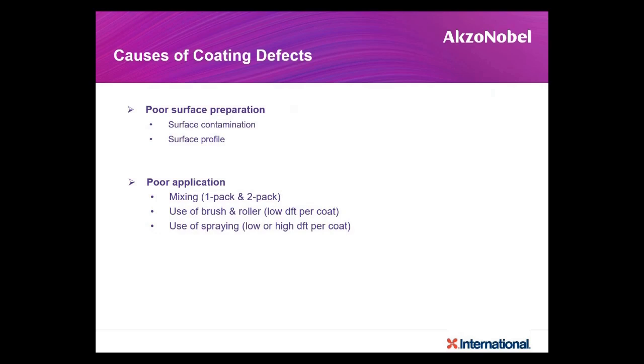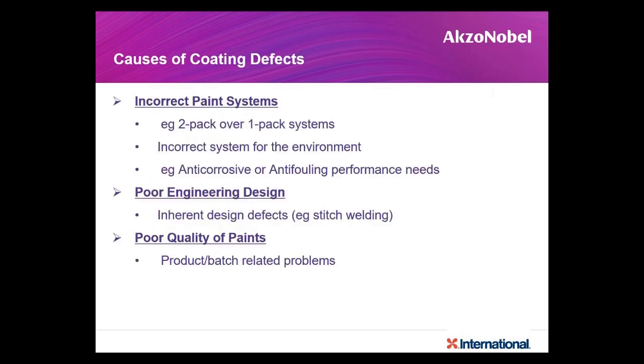Causes of coating defects can start from poor surface preparation, surface contamination, higher surface profile, poor application, improper mixing, use of brush and roller improperly, low and high DFT, overspray, dry spray. Then it could be due to incorrect paint systems. Instead of using a 2-pack system, a 1-pack system was used. Incorrect system for the environment, for example, for a C5, a C1 system was used. It will naturally fail. Some of the objects are designed very poorly, with poor access to coatings. So such places will have issues.